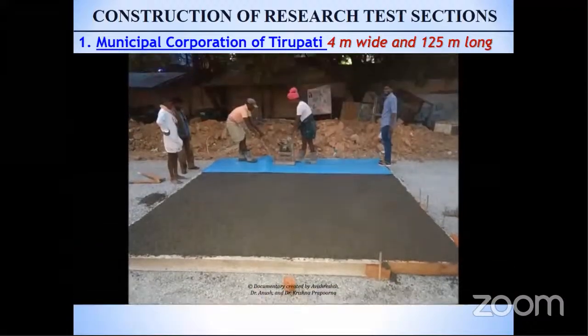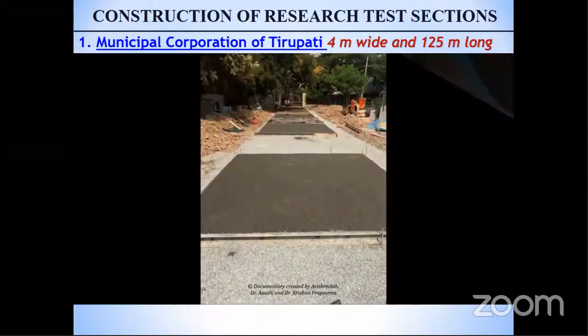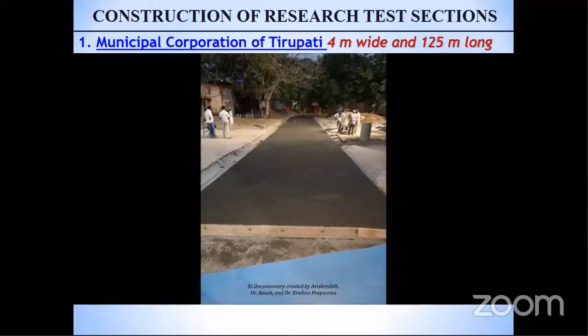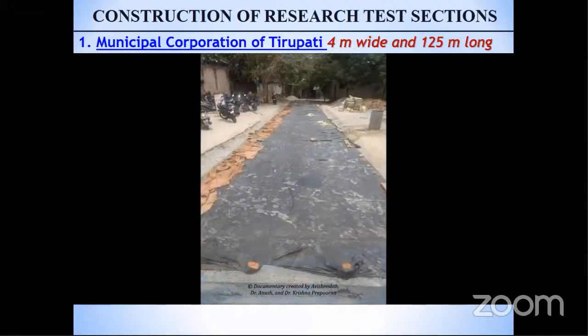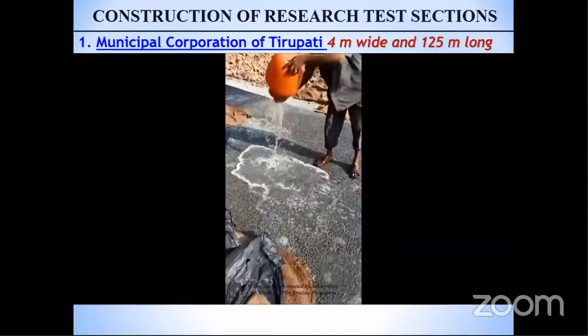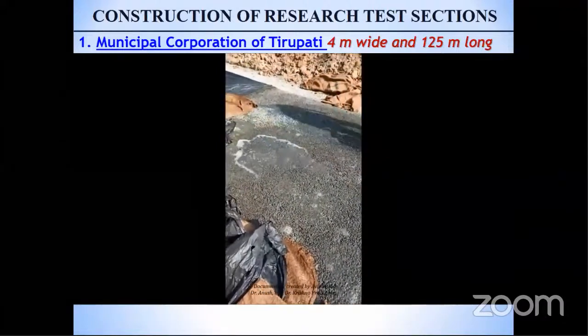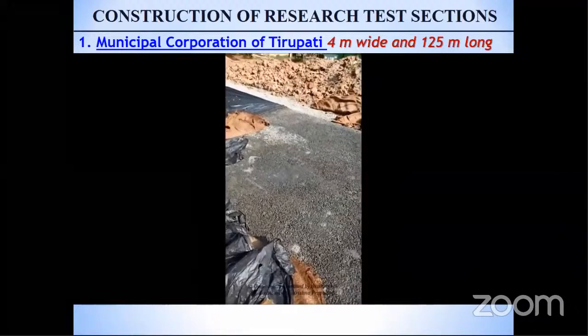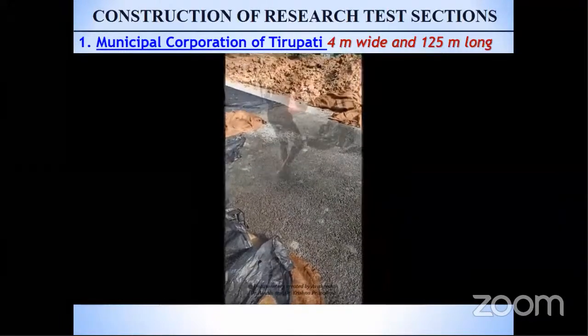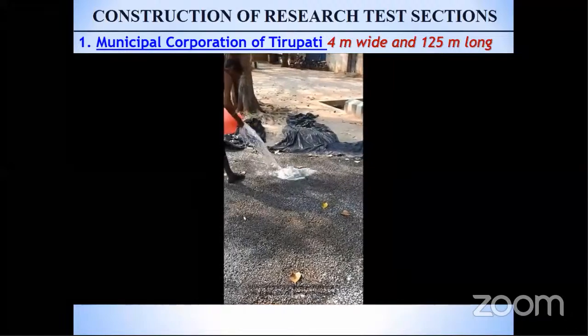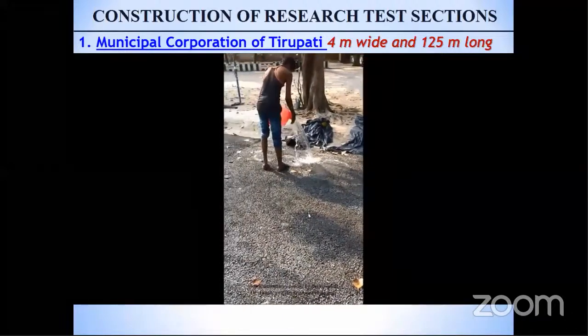This was basically a field laboratory that we constructed for research purposes. Alternate panels were constructed and the pervious concrete was compacted with the help of a vibratory plate compactor. The whole idea of constructing alternate panels was to make sure that the isolation joints were created without any deformations. Once the stretch was constructed, it was cured for about 7 days, and this was the final view of the test section. In these videos, you can see the water being poured onto the freshly constructed pervious concrete pavement, and you can see the rate at which it is percolating into the ground.